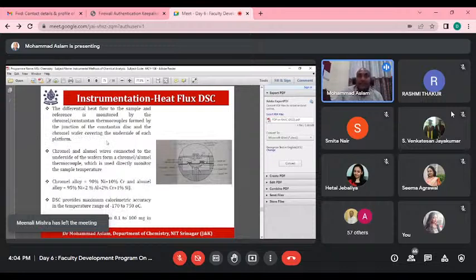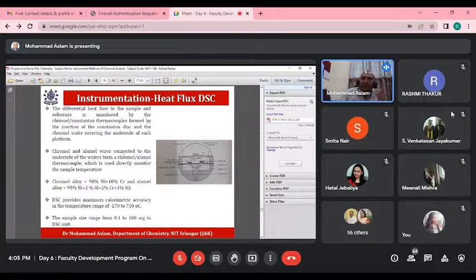platform. This heat is transferred to the sample and reference with the help of the Constantan disc. And this differential heat flow, that is called delta H, basically, the heat flow to the sample and reference is monitored by the Constantan thermocouples, which are formed at the junction of the Constantan disc in between. There are four wires, basically the central joints. And these chromel and alumel wires are connected to the underside of the wafers to the thermocouple, which is directly used to monitor the sample temperature.